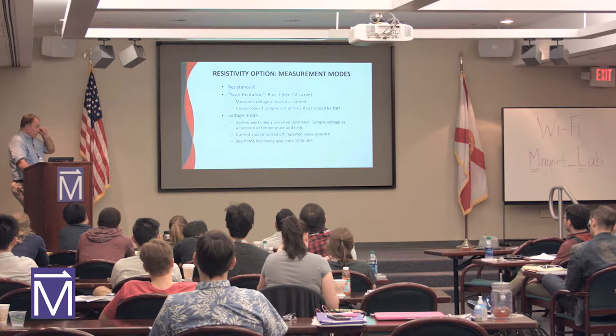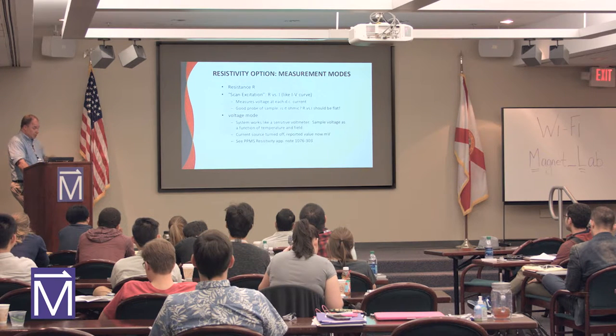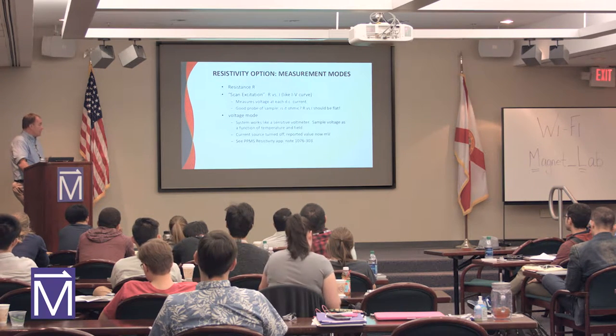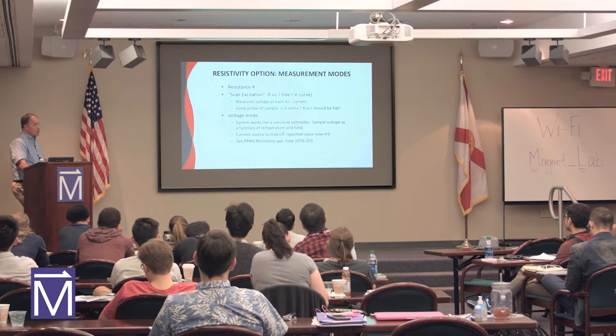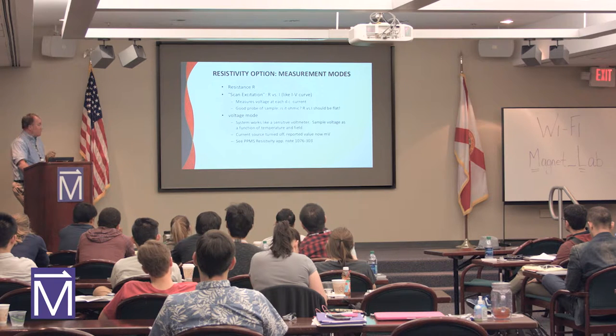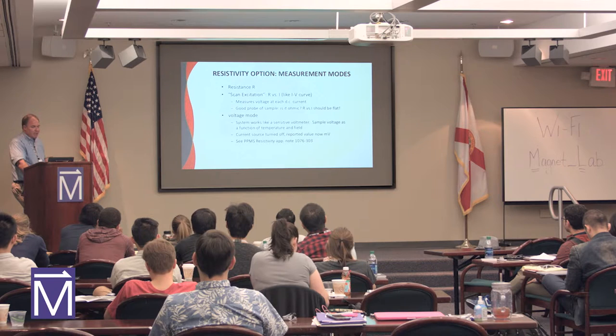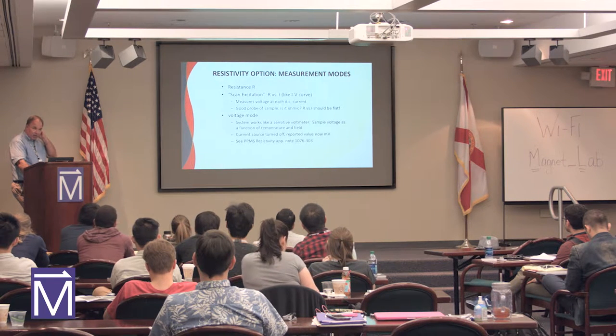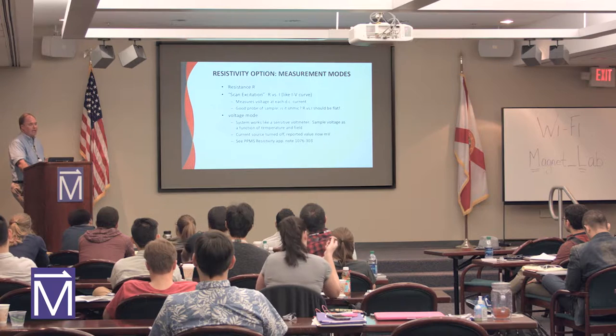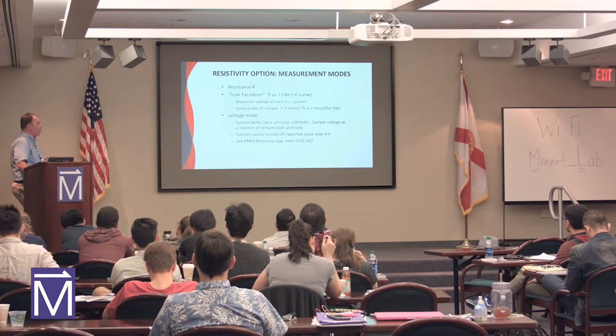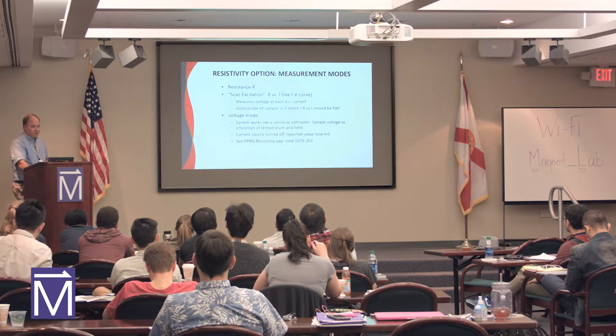We're doing the resistance measurement with the resistivity option. Scan excitation mode measures the voltage at each DC current, like an IV curve. And then you can also use the system in a voltage mode, so it's just a voltmeter. You can have a voltmeter across your sample to see if there's any induced voltages due to temperature or magnetic field changes. So it's another mode that you can run.